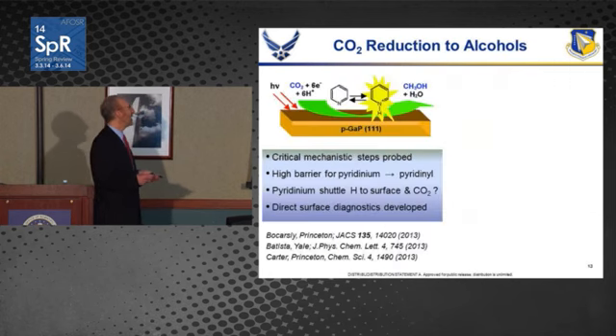Another approach that we're looking at is CO2 directly to alcohols. And this work was motivated by work of Andy Bocarsly at Princeton University, demonstrated a number of years ago, and now being looked at in more detail with electrodes such as this gallium phosphide, but also a wide range of other electrodes as well, platinum, many other metals. And it does turn out that there's a key role that both the electrode plays in this process, as well as pyridine. Pyridine is, again, a co-catalyst here, and we're trying to understand the mechanisms of how this takes place, again, to see if we can enable wider use of this.